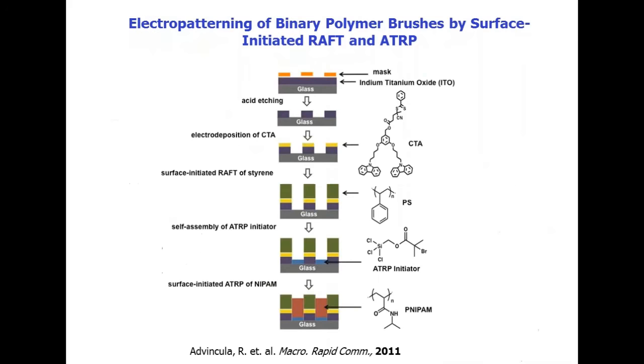We actually demonstrate that this can be patterned efficiently using a patterned ITO. In this case, we pattern the ITO, etch it such that we can polymerize the initiator and grow polystyrene on one side, whereas the rest of the pattern will be exposed glass that can be functionalized with an ATRP initiator. Once we functionalize this remaining portion with ATRP, we can grow another polymer, which in this case is a PNIPAM hydrogel.